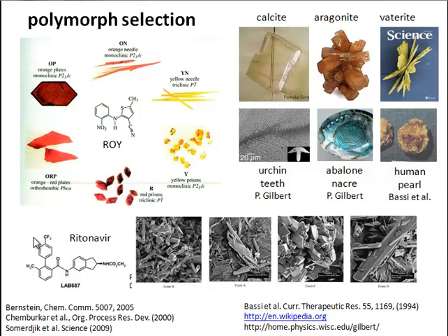From the pharmaceutical side, organic molecules quite often show polymorphism, and a very famous case is ritonavir, an HIV drug that was being produced and sold by Abbott Pharmaceuticals when a second polymorph was discovered. It was discovered because the gel caps began to crystallize, despite being formulated in a way that made them stable towards crystallization of a known polymorph. They were unstable towards crystallization of another one, and this new polymorph was basically completely insoluble.